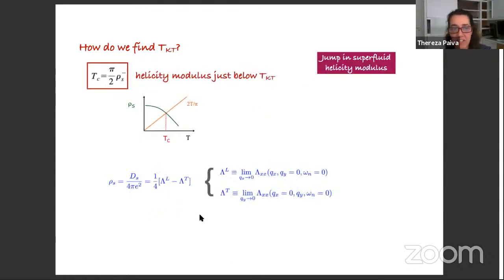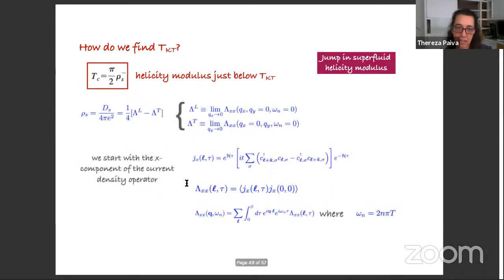And the other way of extracting the Kosterlitz-Thouless temperature is through the helicity modulus. And so the helicity modulus is expected to have a jump here at TC. So if we plot this line here, which is 2T over pi, and the helicity modulus, where they meet is an estimate of the ordering temperature. And so we extract this helicity modulus. It's basically dependent on the Drude weight, and it's given by the longitudinal and transverse, let me go to the next slide, parts of the current-current correlation function.